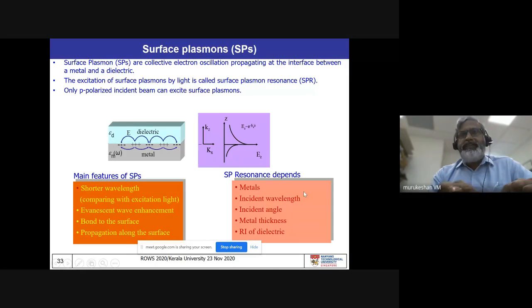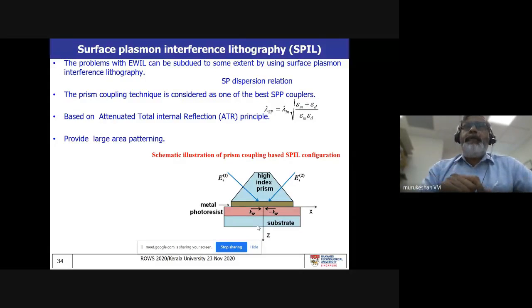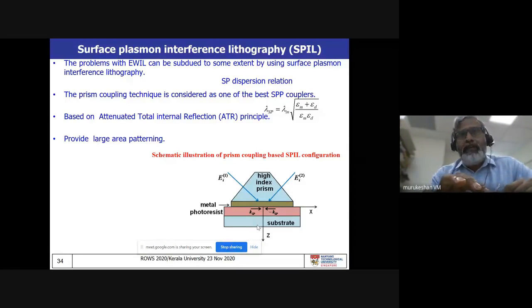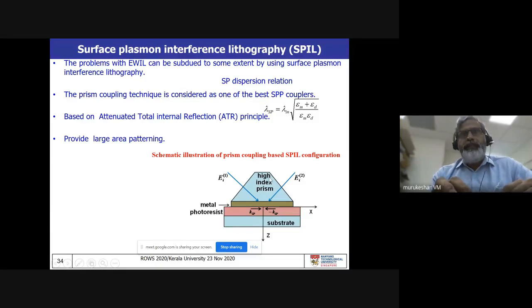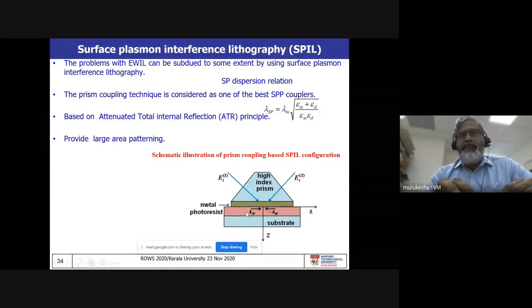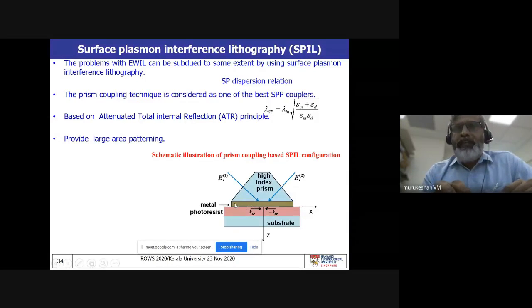And by optimizing these factors, you can actually get a very interesting pattern dimension when you do the patterning. What you need to do is use a high index prism. This is a prism based, Kretschmann type configuration. You have the normal substrate and the photosensitive medium here, and between them, instead of staying in the evanescent wave regime, you put a metal there, and the metal is going to give you the plasmons.